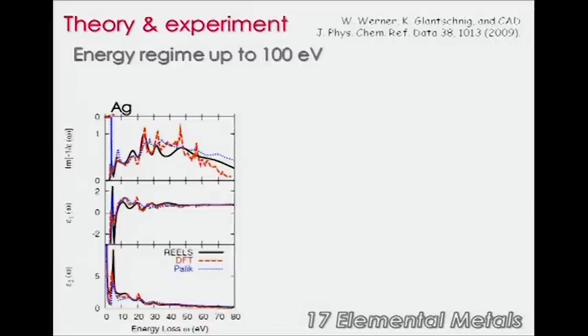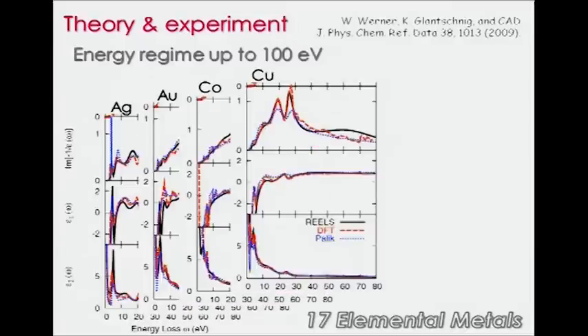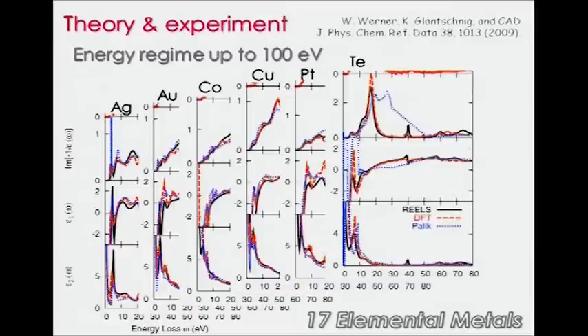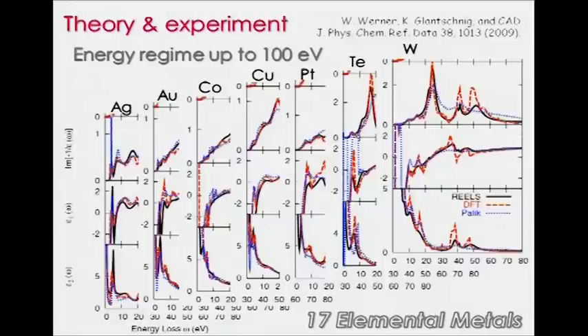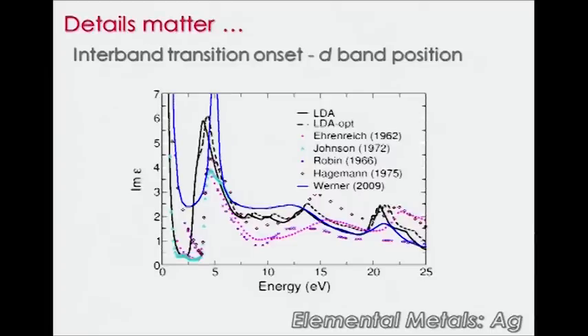So let's go through this, starting with silver, gold, copper, whatever. We were calculating quite a few materials, and we find actually all the trends all over the place. Summarizing, there's excellent agreement up to 100 electron volt. The new experimental data agree much better with DFT, but of course, if you look into the details, these details matter. And to this extent, I just pick out one example, and this is silver.